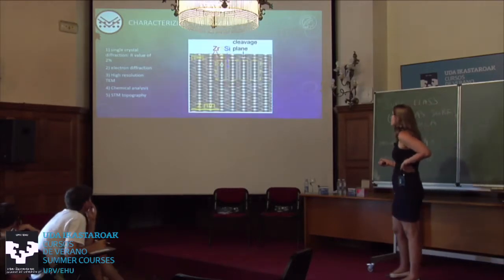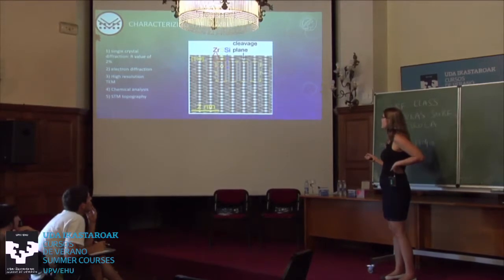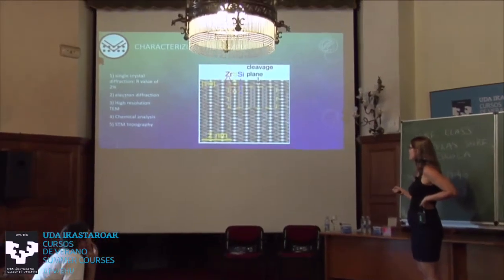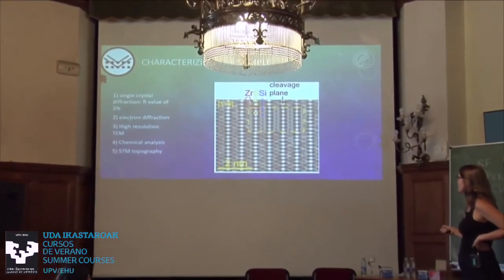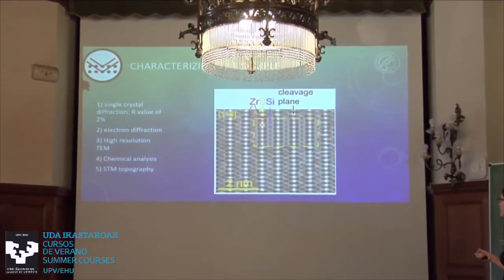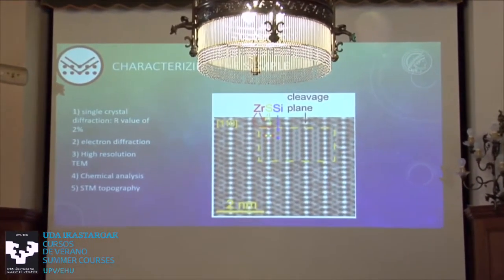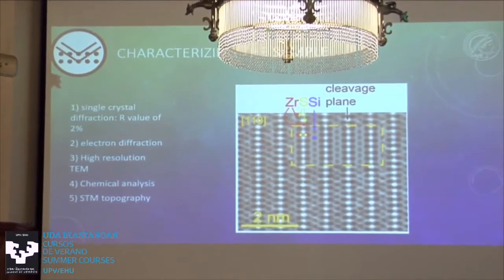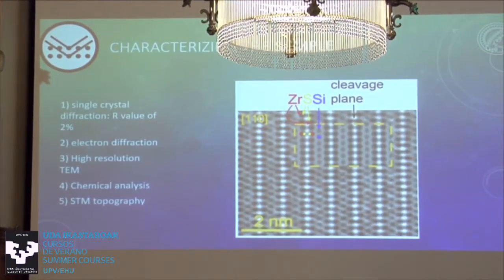We also did some high resolution TEM where you can resolve the individual atoms. So in here is the simulation, and here is what we actually see. And you see that the simulation based on the known structure is perfect, and we can see each individual atom where it's supposed to be.